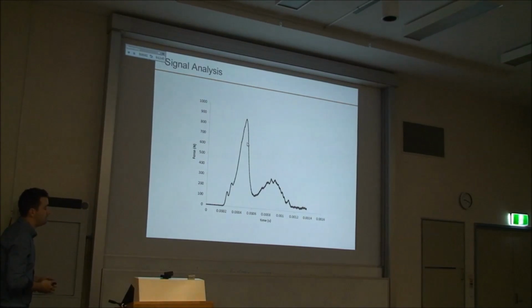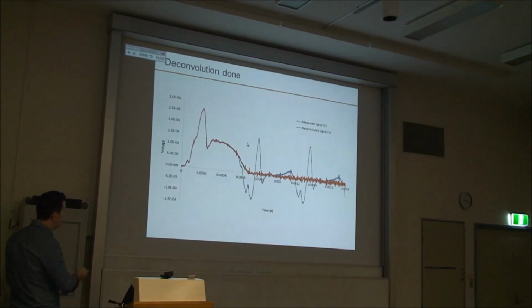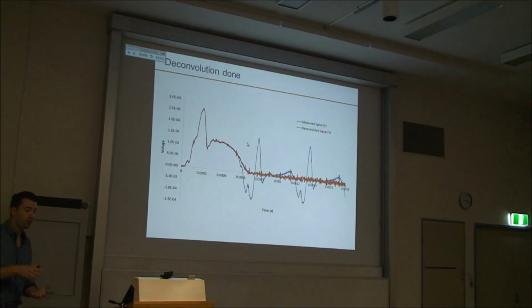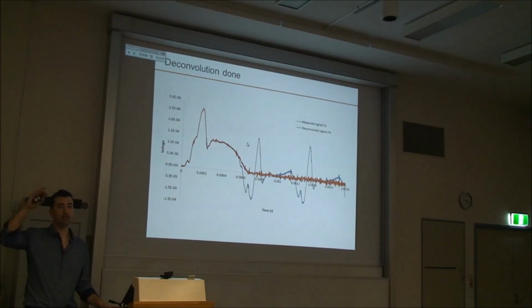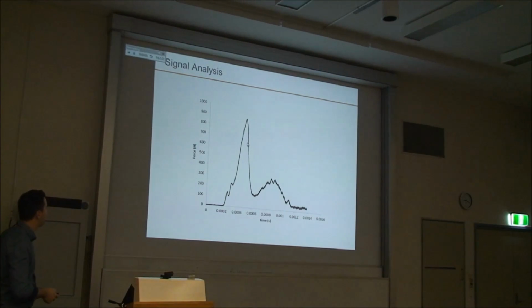So why is it useful? As I said, the voltage is measured by the strain gauge, and the voltage is related to the force. That's just by applying a known force on the bar and recording the voltage, and it's a linear relationship. So then you come up with the force and time profile. This is a particle being broken. The particle is being compressed, the force is applied on the particle, and at this point the particle can't sustain the force and breaks. There is failure. When the particle breaks, it loses contact between the bar and the ball, and the force applied on the bar is going to drop.